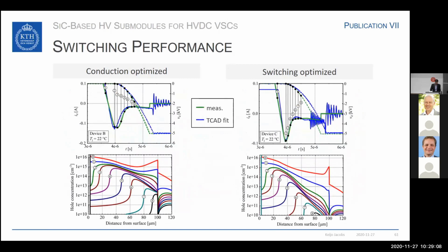We are looking here at the hole concentration inside of the device. On the left side, there is the P+ layer, and on the very right side, there is the N+ buffer layer, and in the middle is the drift region. As you can see here in the drift region, the hole concentration decreases starting from the right side. And the last point where the hole concentration decreases is at the N+ buffer layer. For the switching optimized device, where we have irradiated this region between 80 and 100 micrometers, you can see that the hole concentration decreases quite quickly in this area.